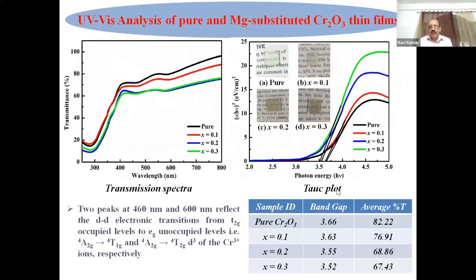Now let us come to the final experiment. The aim is transparency and conductivity. Another experiment, we try to understand the mechanisms of that. Now here you see the transparency in the visible region starting from 400 nanometer to above 800 is around 70 to 80%. Here you can clearly see, if you put a film on a paper, how nicely you can read behind it with your open eyes.